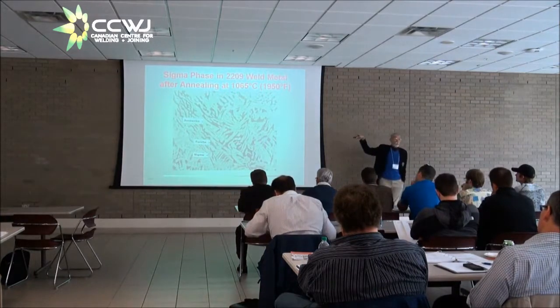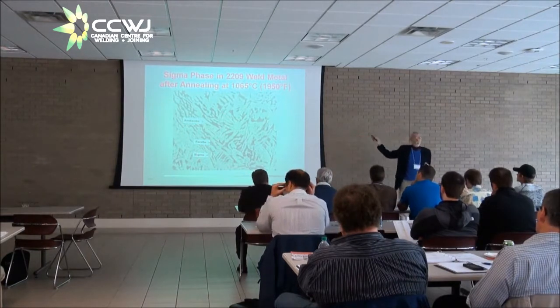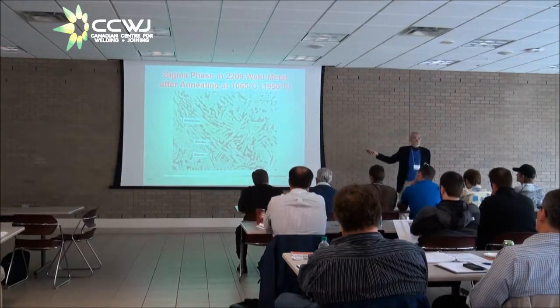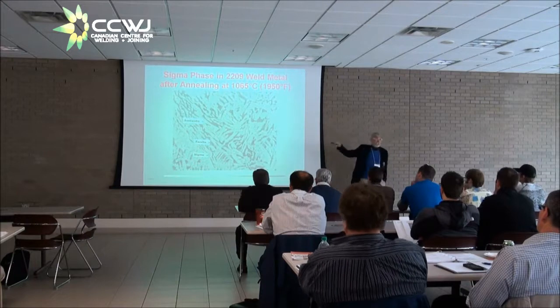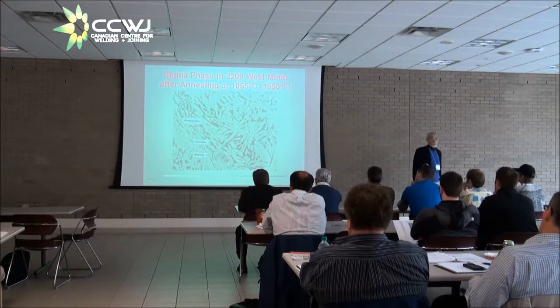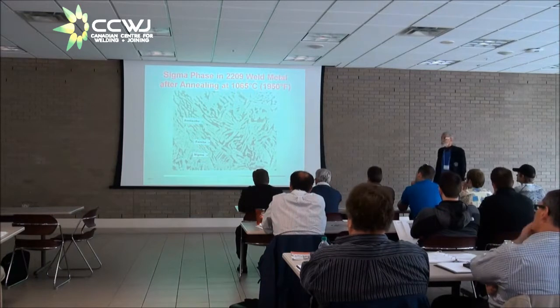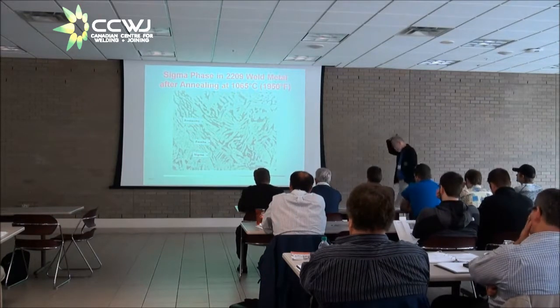In the as-welded condition, I measured the ferrite content of that weld. And it was 45 ferrite number. I use a magnetic method to measure the ferrite. 45 ferrite number. In this condition, it was 22. In other words, half of the ferrite was gone. So I said, well, maybe we just didn't anneal it long enough.